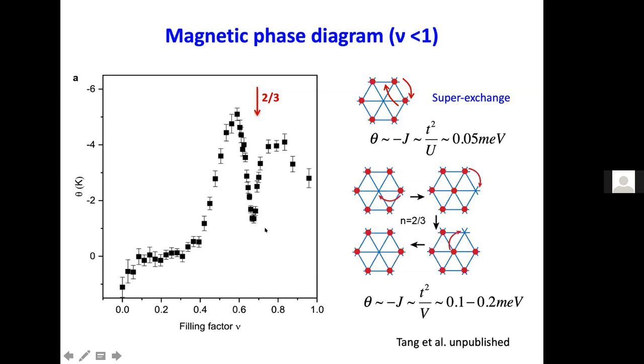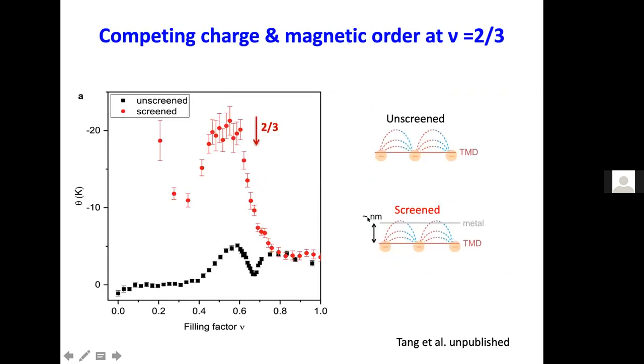Basically, what we saw here is competition between charge order and the antiferromagnetic exchange. To test this, you need to kill the charge ordering state, and we do this by putting a metal very close to the system to screen out the long-range Coulomb interaction.